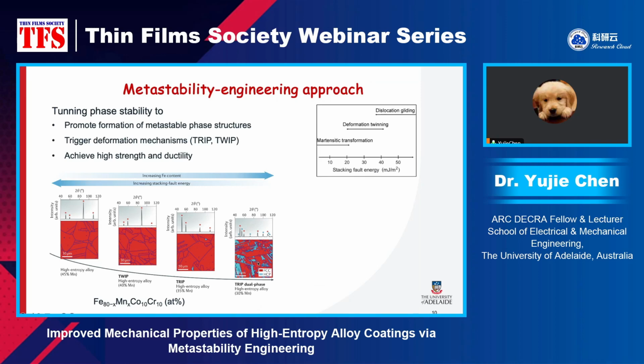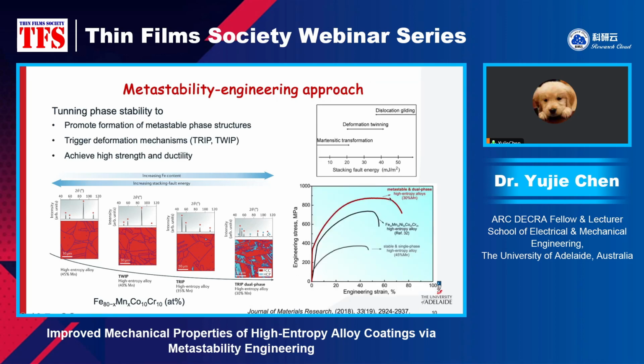Another benefit of this structure is that because the FCC is metastable, during the deformation it will transform to HCP. We know that HCP is harder, so it will cause dynamic strain hardening. That will increase the ductility of the material. So as a result, we can see this is the metastable high-entropy alloy, and this is the single phase one. We can see both strength and ductility have been significantly increased due to the dual phase microstructure and also the transformation hardening.